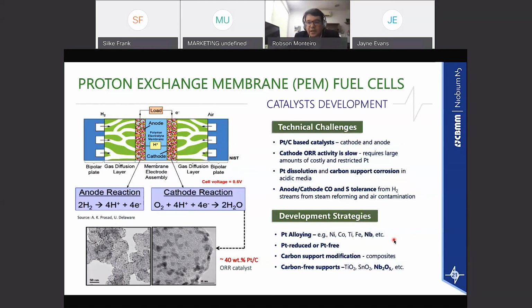Another problem is the acidity of the medium that causes corrosion, platinum dissolution, and carbon corrosion. There is also a great challenge that depends on the source of hydrogen. You need CO and sulfur tolerance for hydrogen streams from the hydrogen source, or even air contamination; this catalyst needs to tolerate a certain level of those poisonings. In terms of strategy, people are trying to alloy platinum with different types of transition metal, even niobium. They try to reduce platinum or even get rid of platinum with a platinum-free catalyst, to modify the support in order to make platinum better dispersed, more active, and use less platinum, and also carbon-free support, where niobium is also being considered.